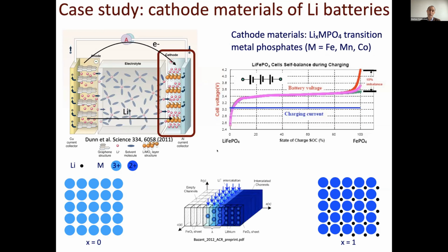So lithium, while arriving at the cathode, lets the lithium-rich phase grow at the expense of the other, lithium-poor phase, which shrinks correspondingly. And this is what we have, except for a thin interface region, which we will neglect today in the thermodynamic limit.